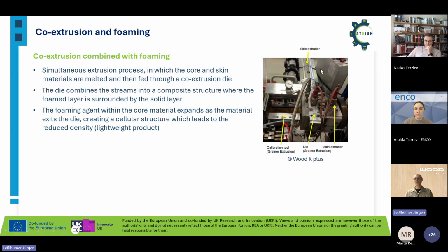Here you can see a picture from our process. We have the main extruder, then the side extruder, then the special die for the combination of co-extrusion and foaming. And when the profile leaves the die, we have this calibration tool to fix the structure and also the foam structure.